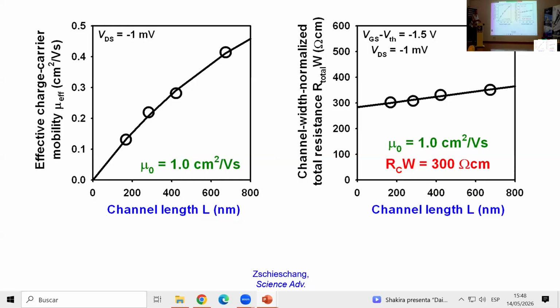So these two parameters are not accessible by measuring just one single transistor. But by measuring transistors of different channel lengths, we can solve for the channel length, and thereby we can then solve for these two parameters. And the values that we get are 1 centimeter squared per volt second for the intrinsic channel mobility, and a value of 300 ohm centimeters for the contact resistance. And so this is why I was using these values earlier in the numerical analysis.